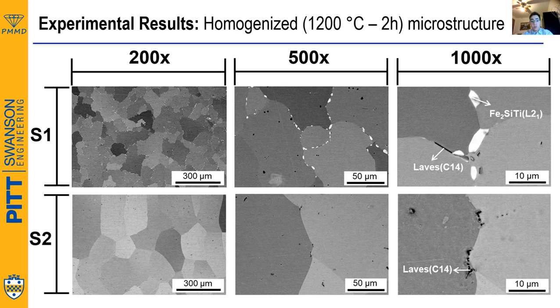L21 in S1 is exclusively along the grain boundaries. Then if we compare the S1 and S2 images, it's clear that the L21 is refining the grains by hindering grain boundary motion, something that was not expected, but is interesting to see, since having phases that work both as a strengthening precipitate and a grain refiner is a huge advantage, because this can lead to improvement in mechanical properties.